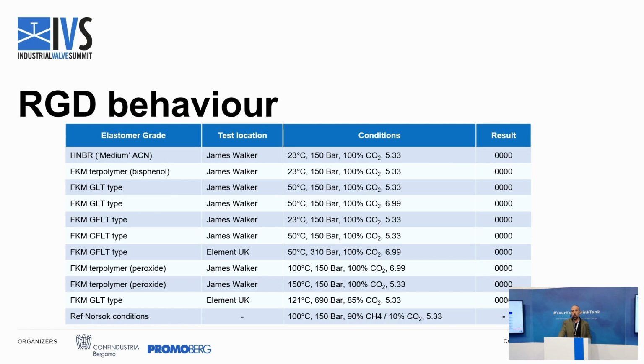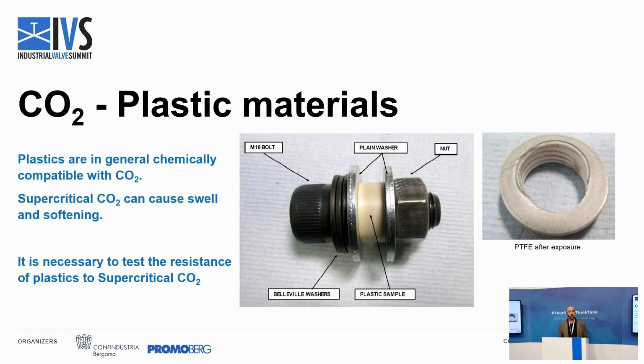Okay, we can have the same problems with CO2, not from the RGD point of view, because RGD is not an issue for plastic materials, but plastics, again, are generally compatible with carbon dioxide. There's no chemical interaction between, for example, PTFE and carbon dioxide. There's no interaction with nylon or with polyethylene, but we want to focus on the supercritical state of carbon dioxide. And when it comes to supercritical CO2 with plastics, there are a lot of plastic materials that suffer from permeation of CO2 in the supercritical state, and that causes a certain material softening or a loss of mechanical characteristics.